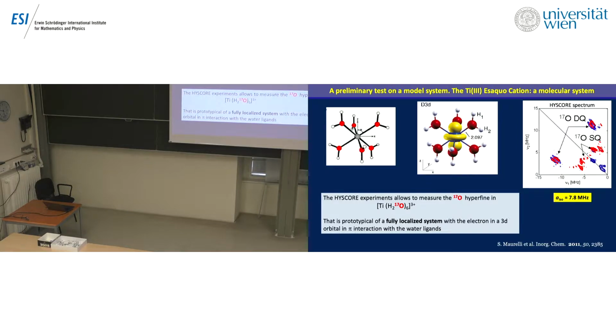To check this, we started, to train ourselves, from a well-defined case. And the well-defined case is not a solid, it is a molecule: the aqua titanium in solution. You dilute this enormously in solution, so you have a molecule, no problem with localization or delocalization. The electron is there in the orbital of titanium, and all the calculations, which are very simple in this case because it is a model, tell you that it's very localized here. So the interaction with the oxygen of the water, which mimics our system a little bit, is recorded here, and you have to keep in mind this figure: about 8 megahertz.